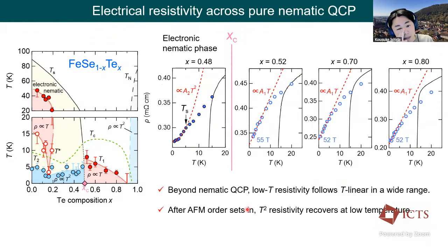Then, how does the resistivity change across the pure nematic QCP? For x = 0.48, which is located just before the QCP, it shows an anomaly around 5 Kelvin, and below that, resistivity shows T-square. This anomaly likely points to the nematic transition hidden below the superconductivity. So again, while the resistivity inside the nematic phase shows a Fermi-liquid-like T-square dependence, after crossing the nematic QCP, resistivity shows a T-linear dependence down to the lowest temperature we measured.